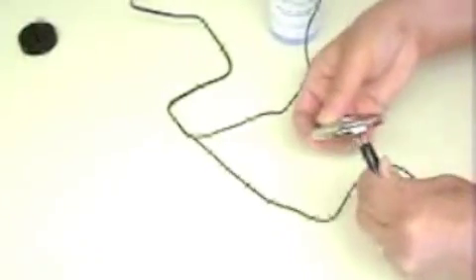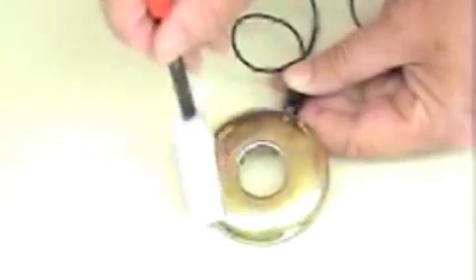Rinse the part off first with some fresh water, preferably distilled. If you have not removed all the chrome it will become very obvious at this point because the gold plate will not attach to the workpiece. Use fairly slow circular motions and dip the wand into the solution on a regular basis to refresh it. As soon as the gold has a good even color you can stop plating unless the part is going to be handled frequently. Then you need to go over it a second time.